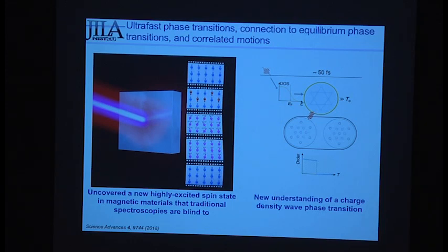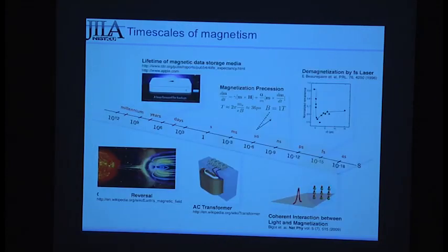Whereas in a material system, the lattice, for the most part, in some cases, if you're looking at a sub-femtosecond dynamic, you preserve all the symmetry and nothing moves. Or if it's a charge density wave material and you're exciting a phonon, you have time to see the emergence of that phonon and you can actually watch the spectroscopy as it changes. So in some ways, attosecond spectroscopy is almost better suited for materials. We can also look at chemical dynamics using attosecond spectroscopy, but it's harder theoretically to know what's happening.